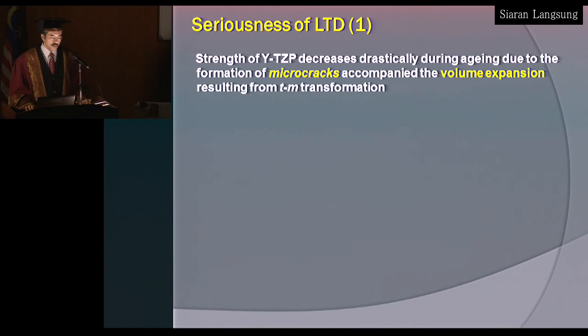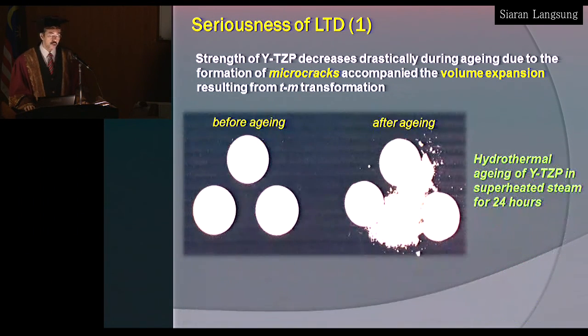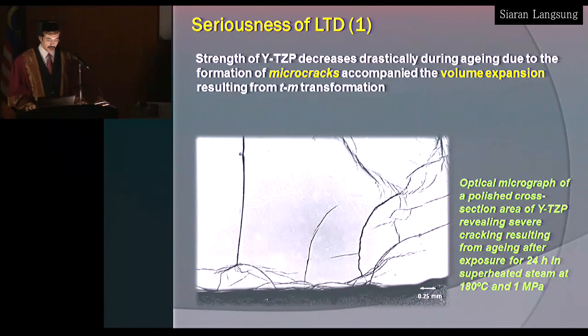Okay, so when transformation takes place, when LTD or low temperature degradation takes place, this is normally accompanied by microcracking because of the volume expansion as tetragonal transforms into monoclinic. And the diagram there shows the samples that have been prepared before and after aging. This material has been exposed to superheated steam for 24 hours. So it breaks or crumbles into powder. And if we look closely into the structure, it developed massive microcracking.